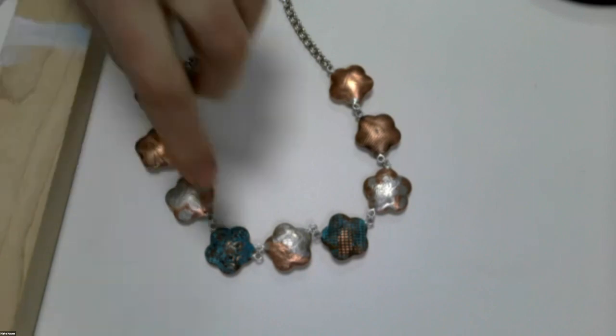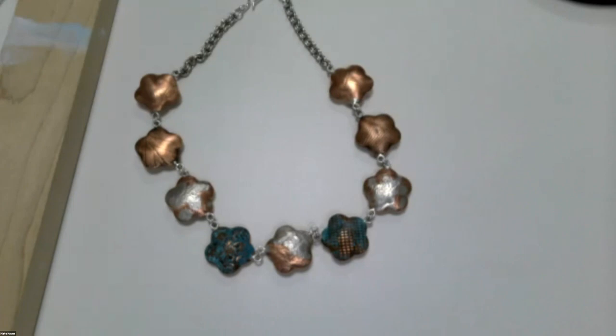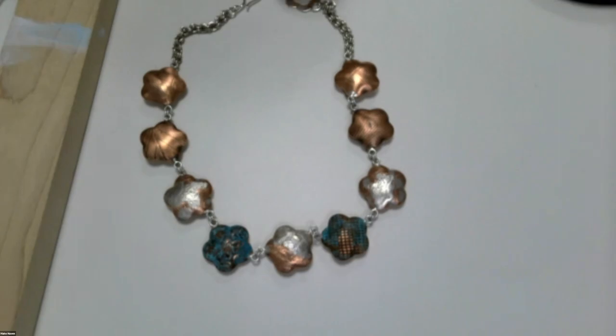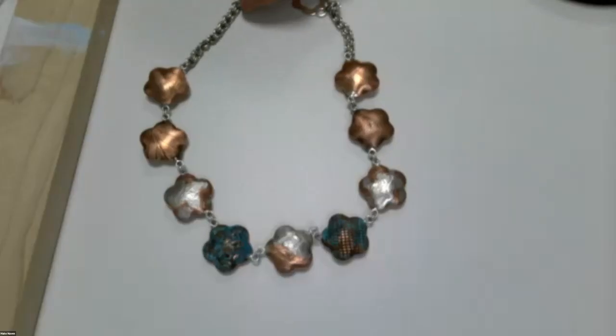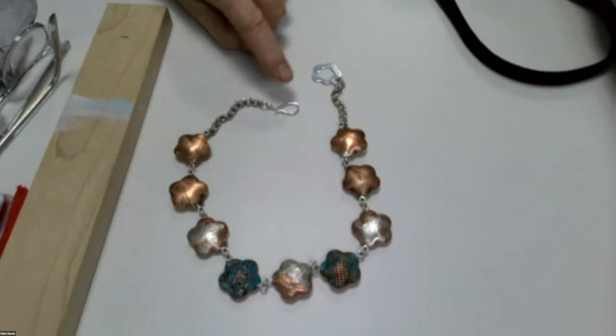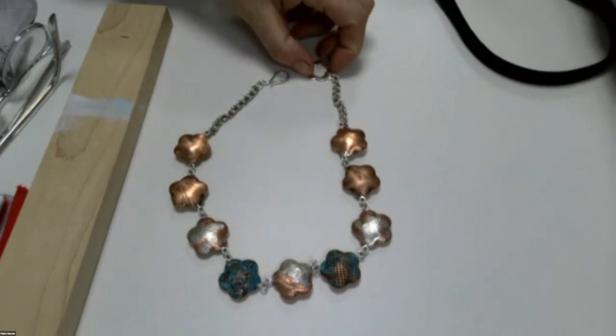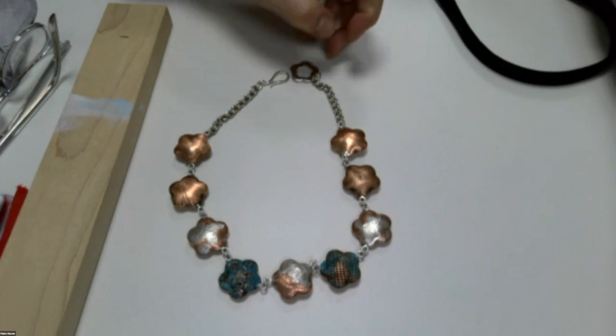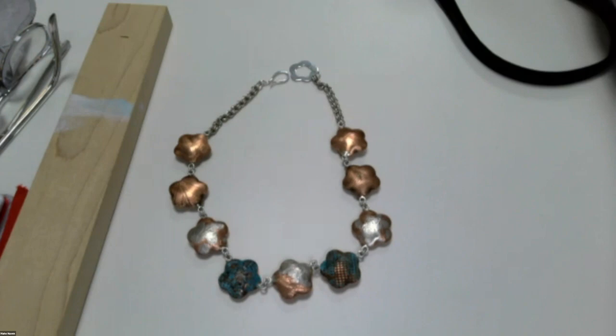There's a lot of steps, and each one of these beads I handled differently, so there'd be a little interest involved. Some of them have a patina. Then I rubbed Renaissance wax on the top so that it would seal the areas that have been patinaed. And on the underside, I sprayed an acrylic spray so that the copper wouldn't rub off on skin, because copper does that. And then these were jump rings that I made out of argentium. And then I made the clasp. The hook and the ring that the hook goes into, I made to mimic the shape of the flower. So that's it.